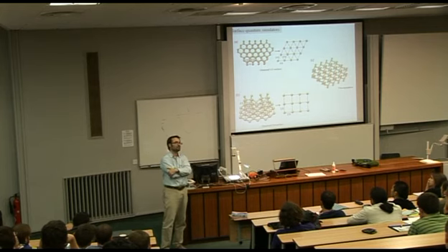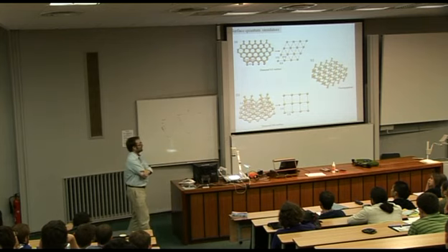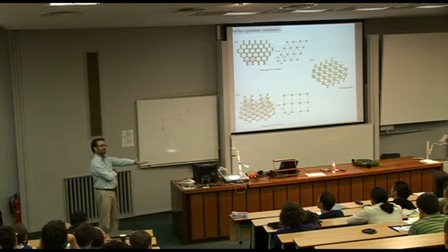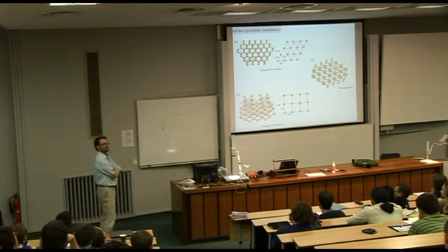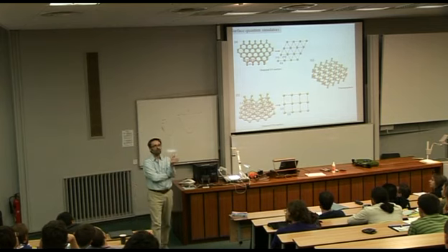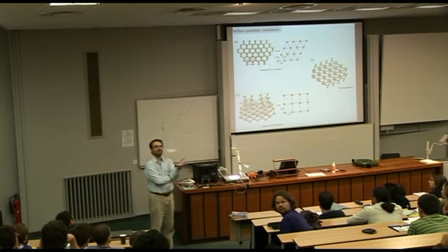And it has a huge band gap of 3.8 electron volt. And so you can actually now put this and lay it on the surface of your diamond, and you have a nice hexagonal lattice of spins. So you can see that you can make a lot of different kinds of lattices here.